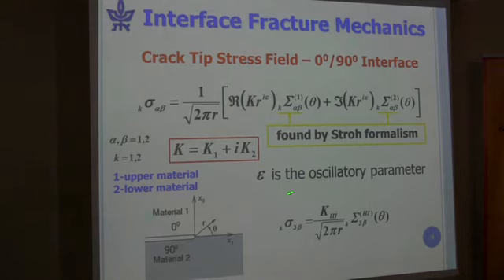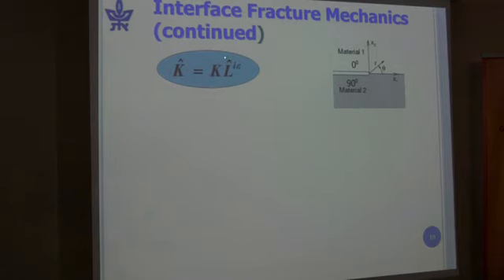And then we can do the same thing for the out-of-plane. And it turns out for 0/90, the out-of-plane behavior is the usual 1 over square root of r. We have K3, the mode 3 stress intensity factor, and we obtain this expression again from the Stroh formalism. So we have an analytic expression for the first term of the asymptotic solution in the neighborhood of the delamination front. And because K has such problematic units, one normalizes by multiplying by a length scale to the i epsilon, and this K hat has normal stress intensity factor units, force times length to the -3/2. And the question is how to choose L hat, and that comes out of the experiments.